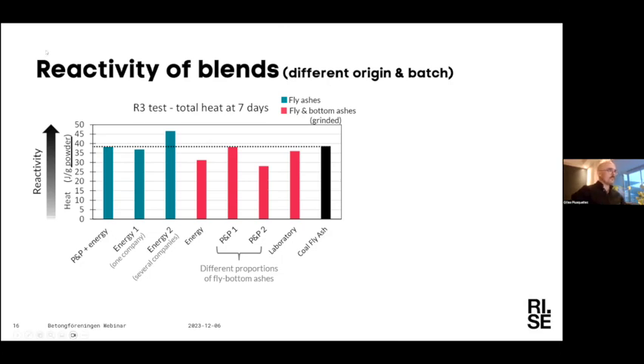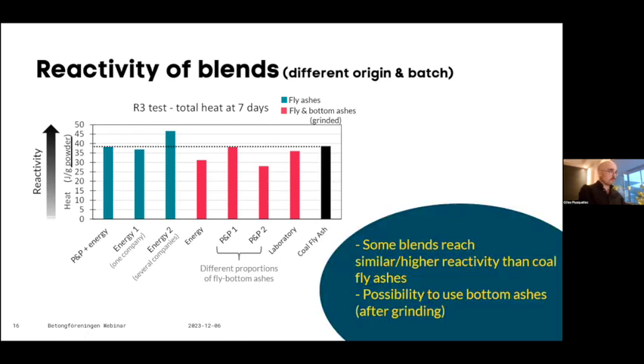So it's different blends, either just fly ash or fly and bottom ashes of different types of industry. And we compare them to a commercial coal fly ash. And the result was actually quite good, with some blends having relatively similar reactivity to the coal fly ash, or even higher in some cases. And it could also show that we could use the bottom ashes after grinding, of course, which was actually a bit of nice news, because in the total production of the biomass ash, it's the bottom ashes that are made the most. So it's good to know that we can actually use them as well.